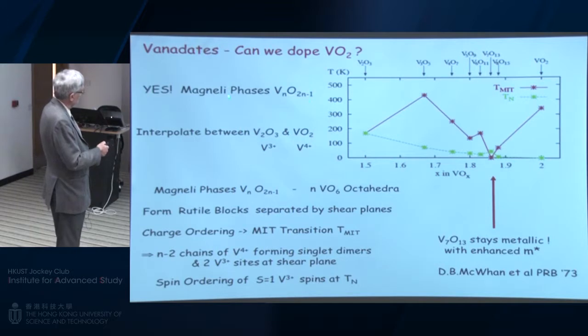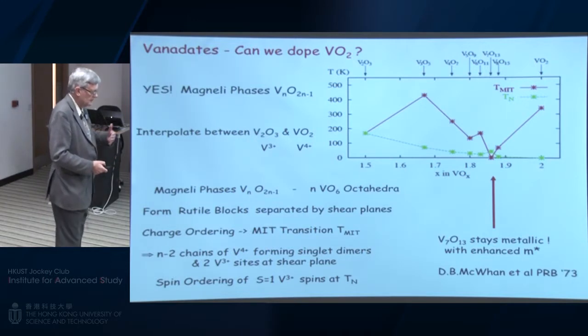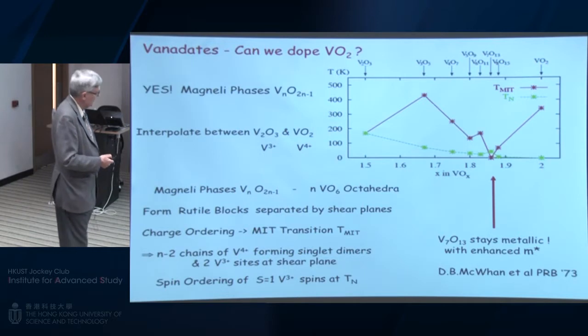Magnéli was a Swedish chemist who discovered a set of compounds. But now here is VO2. If we add one electron per vanadium, 2 electrons is V2O3, and then you have a whole series of crystal phases, VnO2n-1, sitting in between. These are these Magnéli phases, and they consist, you see, of some kind of phase separation. You have n of these octahedra, but n-2 of them form these nice V4+ chains that were the singlet dimers, and the other two, because there's now some 3+ vanadium sites, sit in the shear plane. So there is like a real separation into differently coordinated sites, with some with 3+ and spin one, some with 4+.